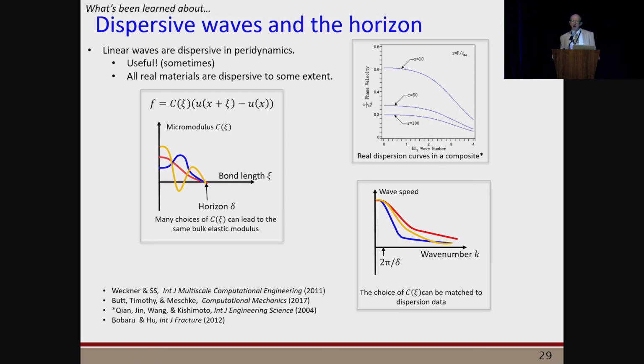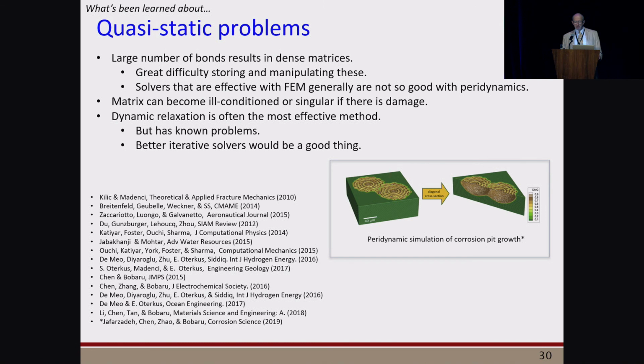Because peridynamics is a non-local theory, linear waves are dispersive, and that's both good news and bad news, as we've learned. It's good news because real materials are dispersive, at least at small enough length scales. So this provides an opportunity to fit measured dispersion data from ultrasonics or other techniques to a peridynamic material model that would reproduce it. However, dispersion can also be kind of a nuisance in macro scale simulations, where it can non-physically alter simulations of wave propagation in some applications.